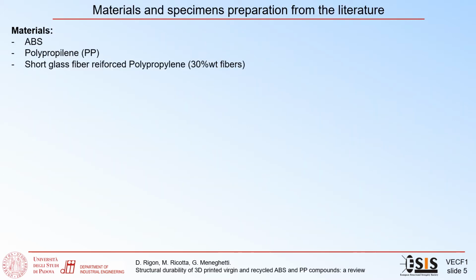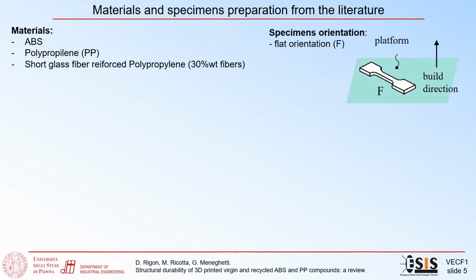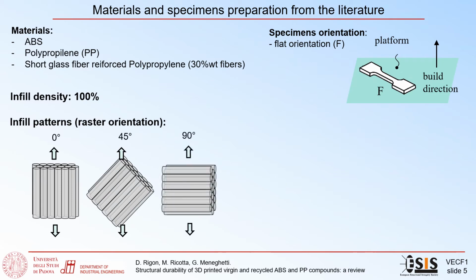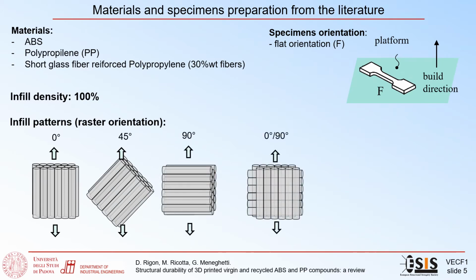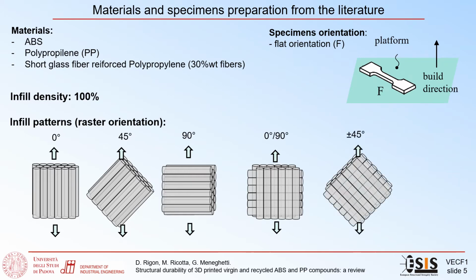According to the aim of this work, we collected static and fatigue test results on an ABS, polypropylene and short glass fiber reinforced polypropylene with 30% in weight of fibers. The specimens were horizontally built with respect to the build orientation with an infill density of 100%. Furthermore, the infill patterns analyzed were 0 degree, 45 degree, and 90 degree ones, and the combination of 0 and 90 degree, and the same combination rotated by 45 degrees.